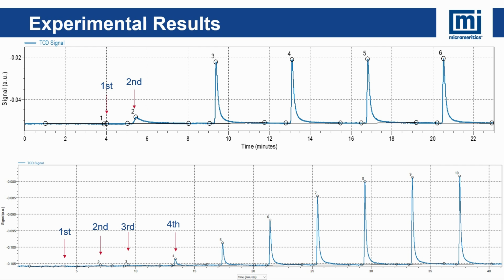When comparing the 2 experimental graphs, it is clear that the control experiment took 3 injections to reach partial saturation stage. In this experiment, the graph showed above, the first injection was fully consumed. The second peak showed some hydrogen gas detected by the TCD, and the third injection approached the saturation stage. In contrast, in the second experiment, the graph shown below, the first 3 injections were completely consumed, and the TCD only picked up the hydrogen signal after the 4th injection.